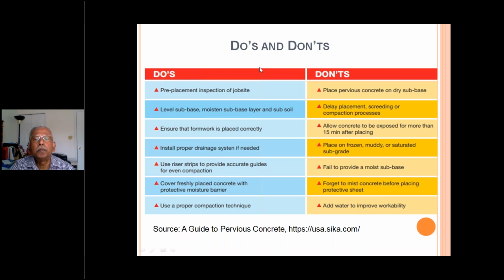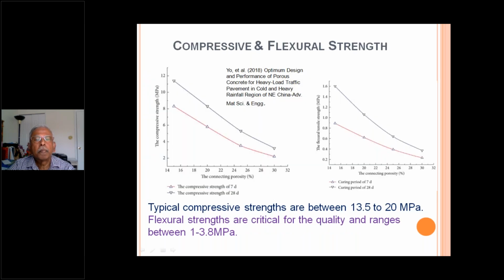Of course, these are some do's and don'ts. I have already discussed all these things. And regarding the compressive and flexural strength of pervious concrete, which is not very important, only when you are applying it in a big road, or heavy loads, it is required. Typical compressive strengths are between 13.5 to 20 MPa. Flexural strengths are critical for the quality and range between 1 to 3.8 MPa.